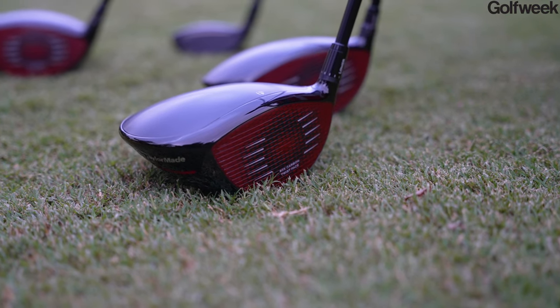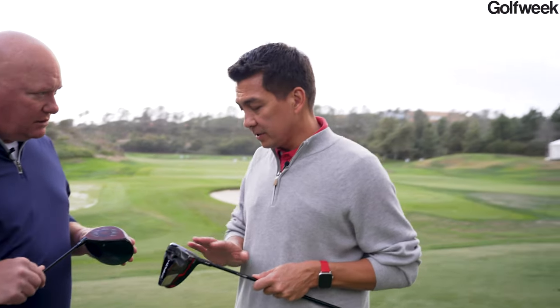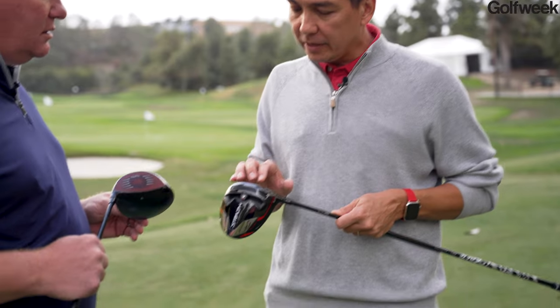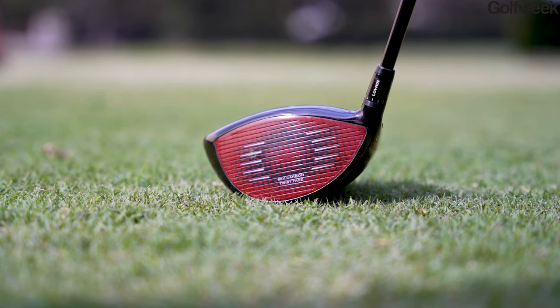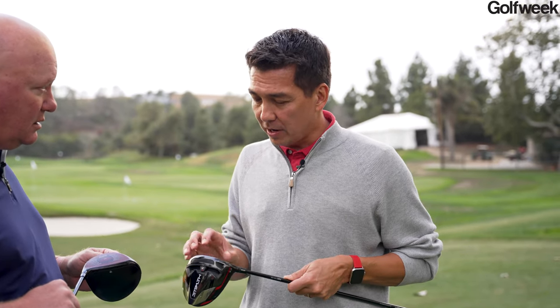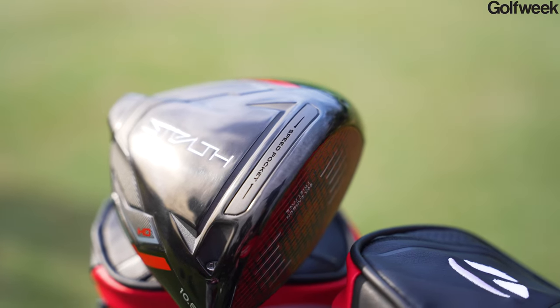Over the top of the carbon fiber, you're not actually hitting the carbon fiber directly. Carbon fiber in itself is a very smooth, slick material, and that presents a problem for golf ball collisions — creating the right spin and launch conditions. We knew early on that to prevent loss of spin in the wet and too much dry spin, we had to do two things: first, put score lines on it to channel away water, and second, create additional friction between the grooves using a nano texture — an extremely fine texture only a few microns high — to give a little more grip on the ball and produce lower spin off the driver.